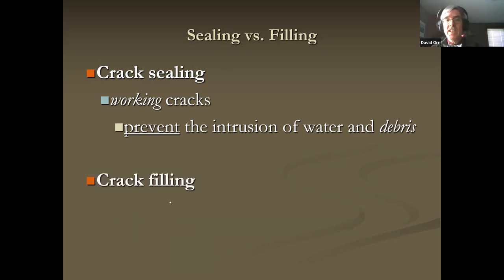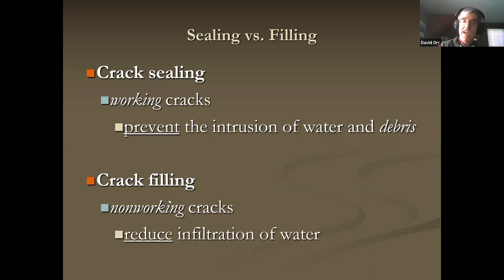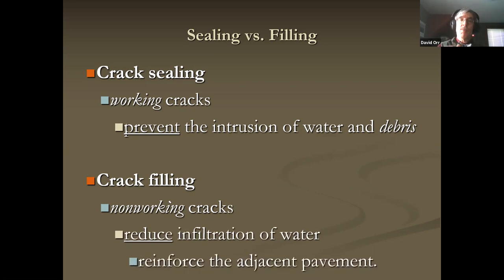Crack filling is for non-working cracks, cracks that are not moving at all, okay? In that case, we can get away with a little cheaper material, and all we really want to do is reduce the infiltration of water. And at the same time, because it's not moving, instead of using a flexible material, we can actually use a material that reinforces the adjacent pavement, okay?